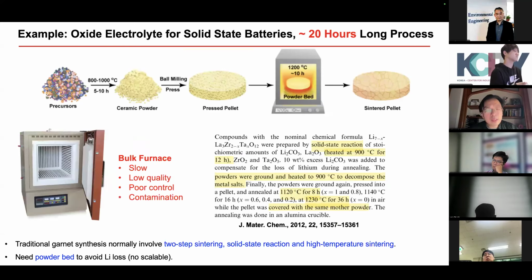And once they discover it, they have to manufacture the material, right? So here is usually the typical process. People take the powder, put it in the furnace, heat it for 5 to 10 hours, then break it again and press it into a pellet. And they heat it again. This step is called sintering. You're trying to make a dense membrane with the right composition. So it takes about 20 hours, starting with the powder. The lithium loss is everywhere in your chamber. You contaminate your chamber, and you don't get good performance because you're using lithium metal. It takes 20 hours, so you don't get the manufacturing speed.